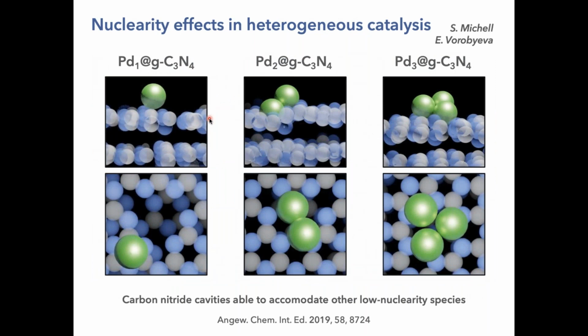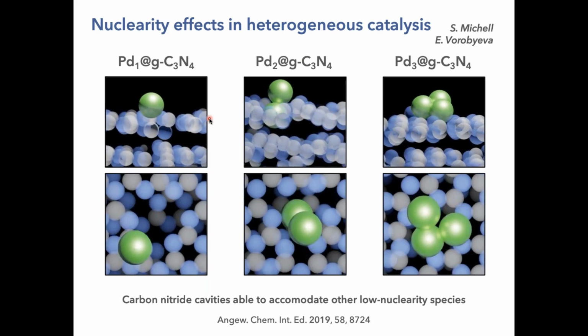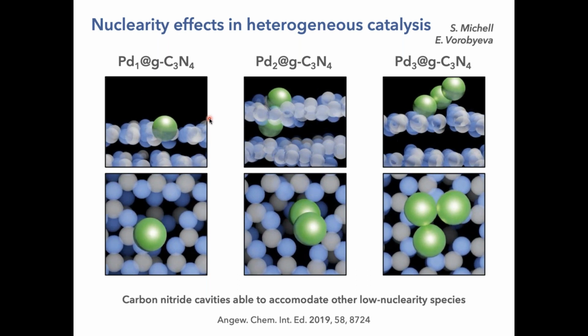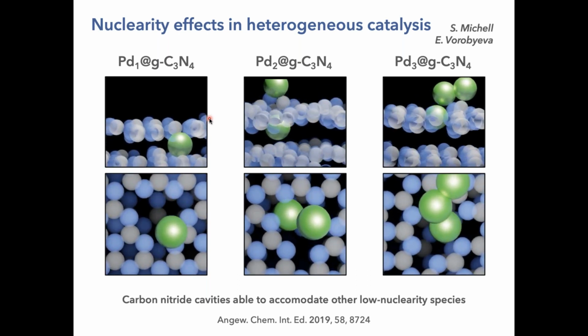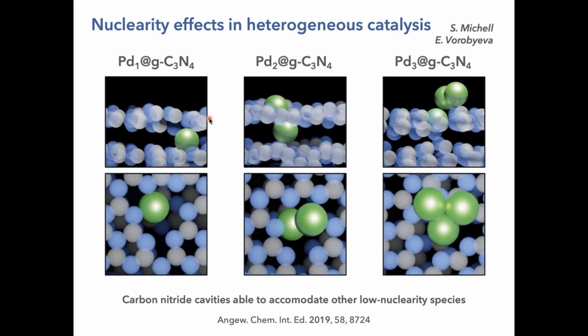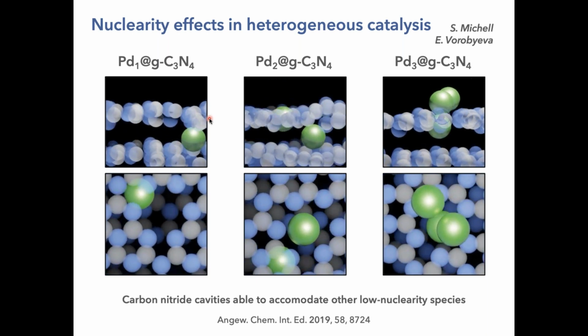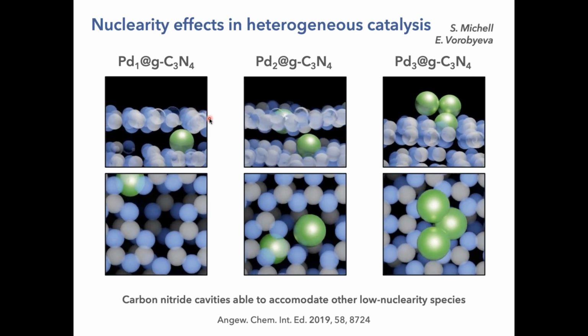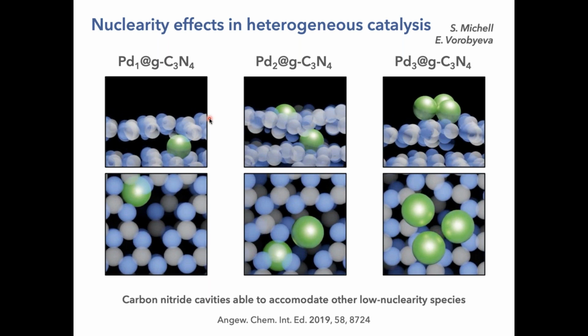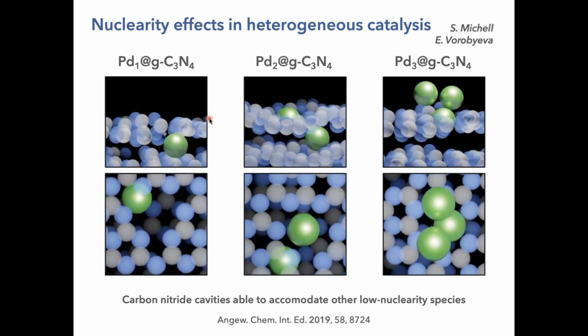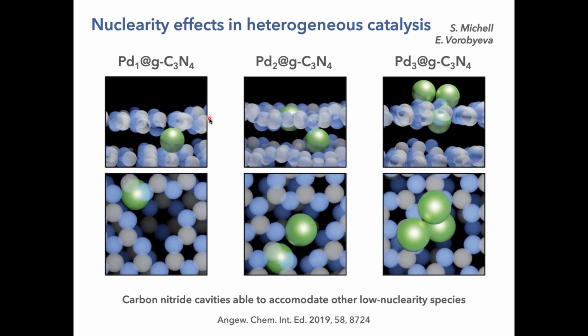The carbon nitride host is also able to stabilize higher nuclearity species. As you can see here, dimers and trimers of palladium. And this has been achieved by depositing metal precursors with the desired nuclearity. And so you can see here some molecular dynamics that shows how these species, the dimers and the trimers, are accommodated in the cavity. And what these studies allow is a platform to derive structure performance relationships with atomic resolution. So you are building clusters with the optimal size, because it's not always the single atom is the best system. It depends on the demands of the reaction.